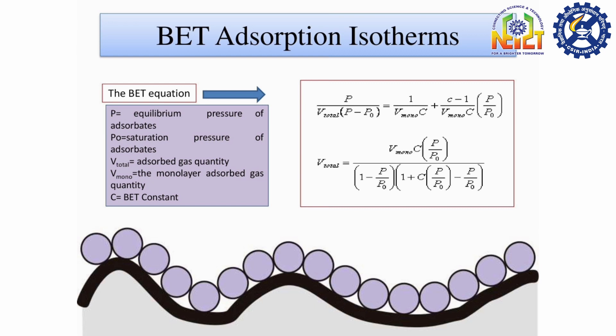Adsorption of nitrogen at a temperature of liquid nitrogen leads to a so-called adsorption isotherm or BET isotherm, which can be measured over porous and non-porous materials. In specific cases, like for zeolites or activated carbons, the use of argon adsorption or carbon dioxide adsorption is often preferred over nitrogen adsorption to accurately probe the small micropores.